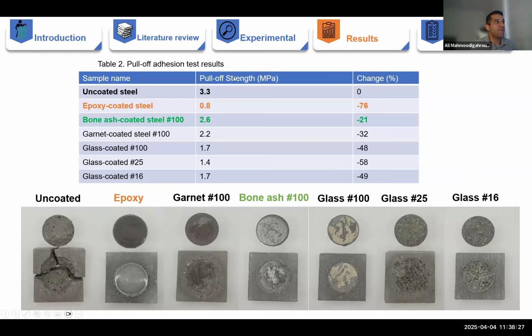For uncoated steel, pull-off bond strength was found to be 3.3 megapascal, which was impressive, and the failure mode was found to be substrate failure, which means concrete block failed before the detachment. For epoxy coated, the value was found to be only 0.8 megapascal, equal to 76% decrease, and the failure mode was adhesive. And for the best samples, the abrasive coated samples, which was bone ash, the bond strength was 2.6 megapascal and equal to only 21% decrease compared to uncoated sample. And the failure mode was found to be cohesive with visible detachments of concrete on the surface of coating.